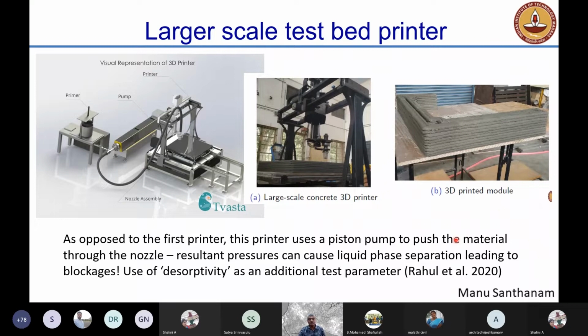a slightly different way of depositing the material. In this case, what we did was we used a pump. Okay, so the material was fed using a primer into the pump. So as the primer pushed, the pump piston basically moved backwards to take in the material. Once all the material was filled up, the piston basically moved forward, and when it moved forward, it started pushing the material into the pipe here, which carried it to the nozzle.